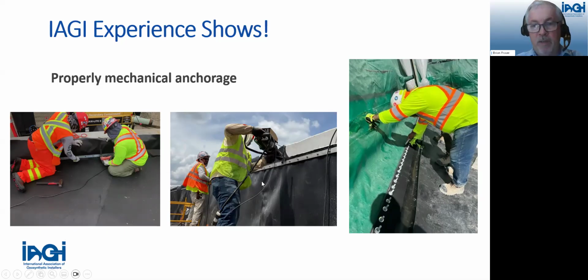Photo in the middle, this is actually a concrete partitioning off a pond, and they're mechanically anchoring on the top to support and anchor the material, as we obviously don't have an anchor trench. And the photo on the right is a challenging application. This is potentially under the water level. It's a spray applied polymer on the wall and a 40 mil HDPE on the liner system using a special transition strip that's welded to the liner and then mechanically attached at 3-inch centers to the spray applied wall, again to make a watertight seam.